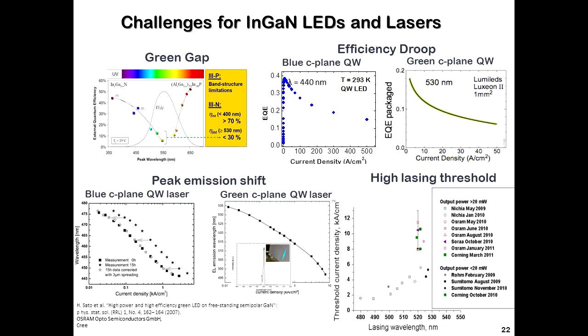With the nitride system, the efficiency goes down, it just cascades down, and when you reach green, it's next to nothing. Now you can approach it with other materials from the other side, aluminum gallium phosphide. You can make red LEDs and lasers and all that, but the thresholds are very high, but that's all we have at this point in time. In the LEDs, there is this very peculiar, unique problem. The efficiency goes down. We call it efficiency droop. So if you're operating around here, you see that the efficiency has gone down by 40% from the peak. And as you go to longer wavelengths, to green and so on, it gets even worse.